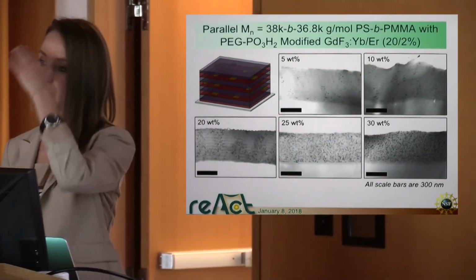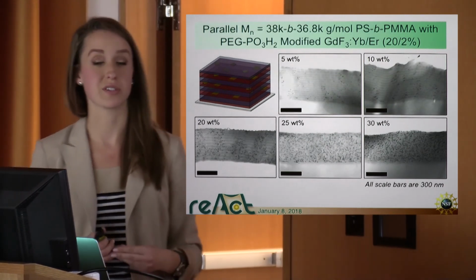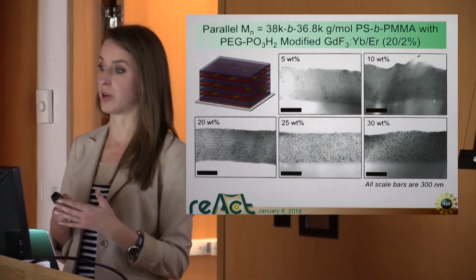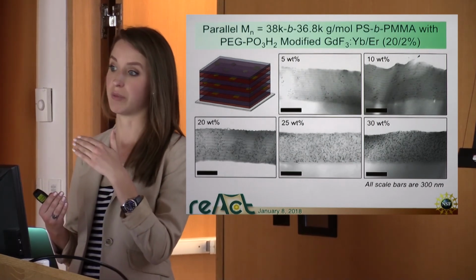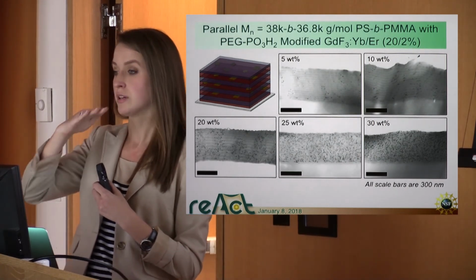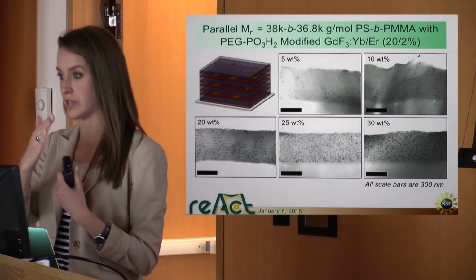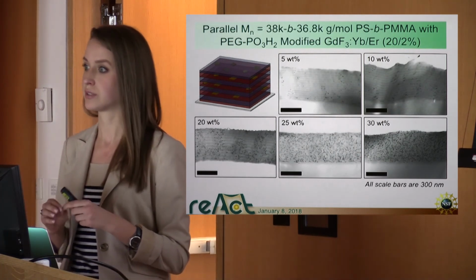Do you think it's really important to have them all aligned very parallel and in one plane to get the final properties that you want? Or there could be some misalignments? I think there could be slight misalignment. I think experimentally, even in some of these images, let's see if I can go back here, there is some slight misalignment even within the domain. So that's something else I'd like to look at, the effect of block copolymer molecular weight, to see how that might affect the alignment just within the domain, and whether there might be more variation in terms of the angle within the domain spacing itself.